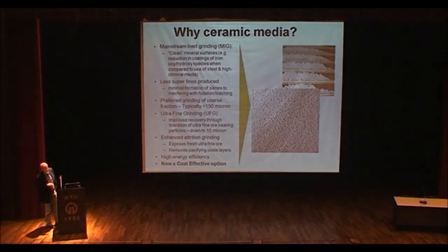The platinum industry uses that to great effect. They've had a 4% increase in their recoveries just purely from inert grinding. If you work out what the platinum is worth these days, it's something like $1,700 an ounce. You multiply that by the amount they produce, it's a very significant value. In fact, they could pay off their entire installation of 22 mills just merely by having the benefit of inert grinding.